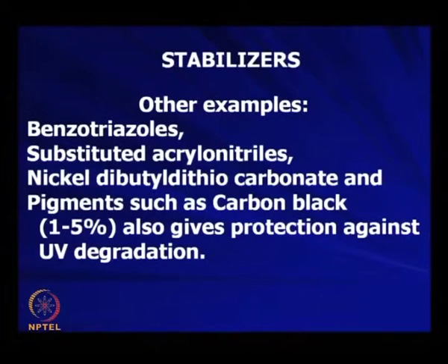I did a substantial level of research in my lab on this degradation and stabilization of polymers earlier. So, my experience is that if you can develop any agent which can break to form free radicals, and if that free radical is stabilized by the group to which it is attached, then that can act as a very good stabilizer for your polymer.